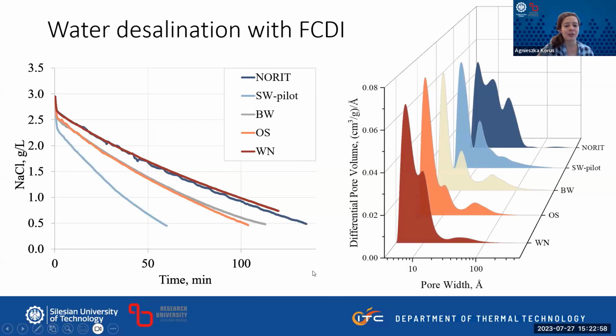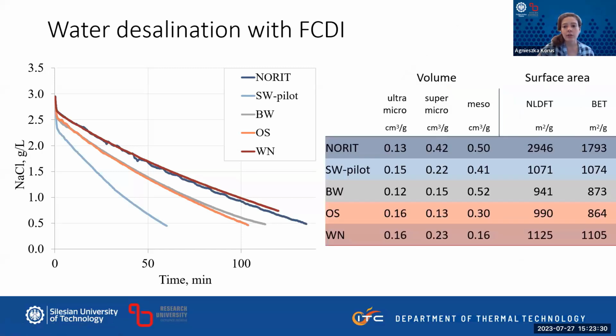So now we really need to focus on finding the reason behind the different efficiency of the chars that we are using, because it's not solely due to the surface development. We believe it's also going to be dependent on the conductivity of the chars and also on the surface chemistry, so functional groups and inorganic content. This is also the table comparing the volume of the pores. You can see that Norit has quite a lot of super micropores and mesopores compared with the other chars.